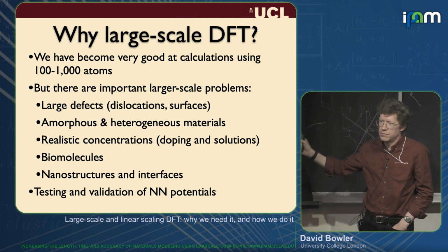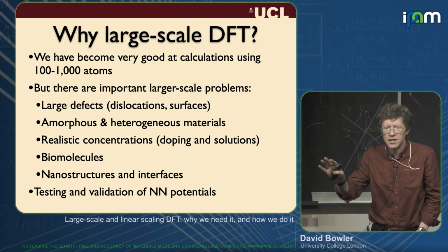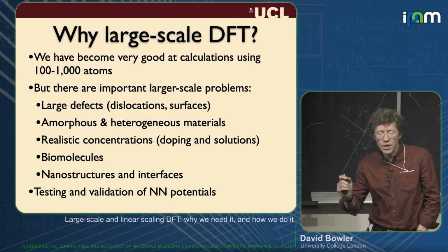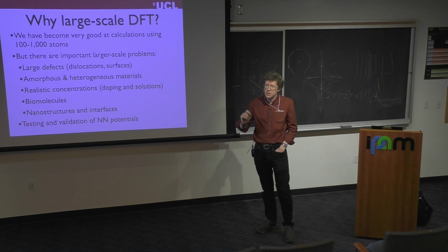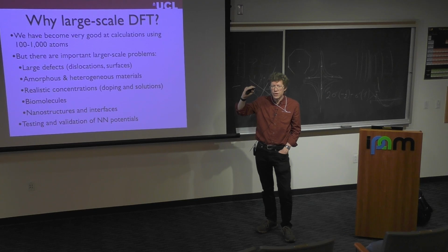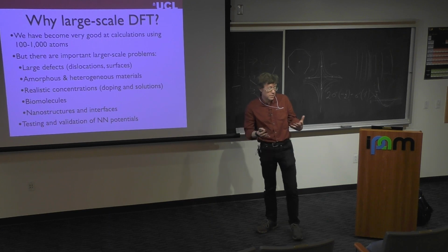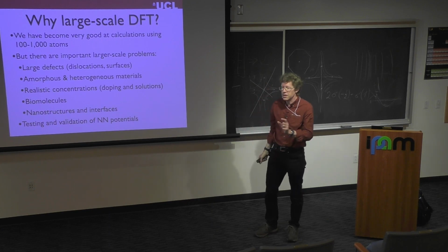So my favorite example here, which you probably have all heard me say before, is the metal insulator transition in silicon. So if you want to do that as an experimentalist, that's 10^19 dopants per cubic centimeter. So if your doping is higher than that, you now have metallic silicon. And that's what people who grow semiconductor devices use to make semiconductor devices conduct.